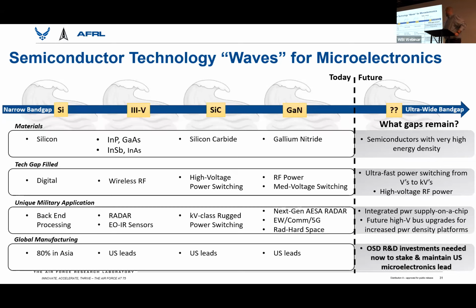And then moving to the right of that black hatched line, we start to get into what we call ultra wide bandgap materials, such as gallium oxide, aluminum nitride, and diamond. The target applications for ultra wide bandgap materials, that's typically ultra fast power switching from the volt to kilovolt range, and high voltage RF power.